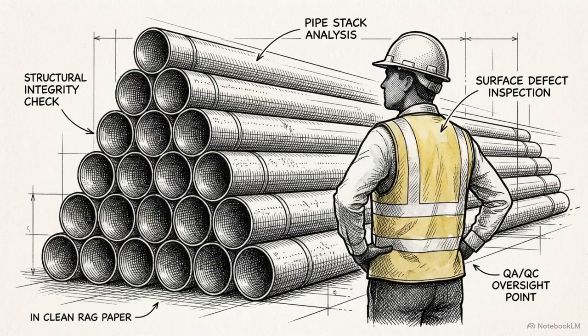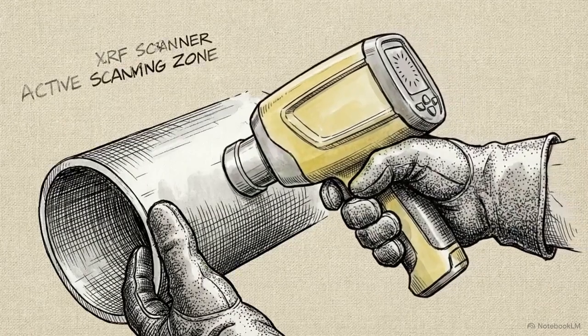Because the MTC was missing, the fabricator relied entirely on visual inspection. They completely bypassed the mandatory Positive Material Identification Test, or PMI. A single inspector with a handheld XRF scanning gun could have prevented this sequence. Pressed against the metal, the gun fires X-rays into the surface, reading the atomic makeup of the pipe in seconds. It would have immediately flagged the missing chromium.